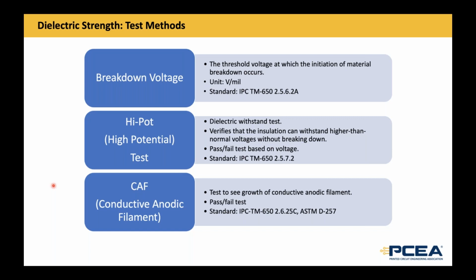High potential test. It's a dielectric withstand test that verifies that the insulation can withstand higher than normal voltages without breaking down. This test is more often used to test thinner dielectric material, like embedded capacitance material under 2 mil thickness, because it's more critical. It's a pass or fail test depending on the voltage, and that requirement will differ based on the application. A commercial application might be 250, but telecom applications that go through a more intense environment will be tested at 500 volts.